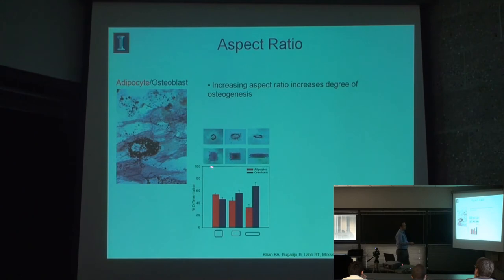And so when we did this with rectangles of the same area, but with increasing aspect ratio from 1 to 1, 3 to 2, and 4 to 1, and we count the cells, we see an interesting trend emerge, where as we increase aspect ratio, we increase the proportion of cells in the culture that are turning into bone cells. In the square, we see about equal numbers of fat and bone cells, but as we go to this longer rectangle, we see more bone.